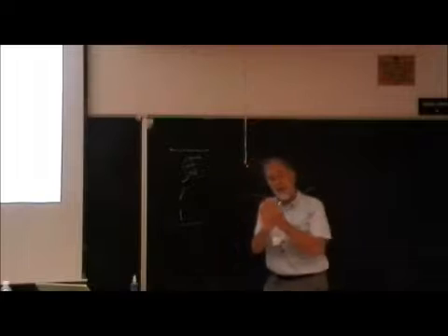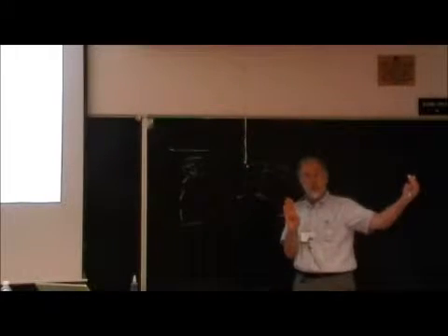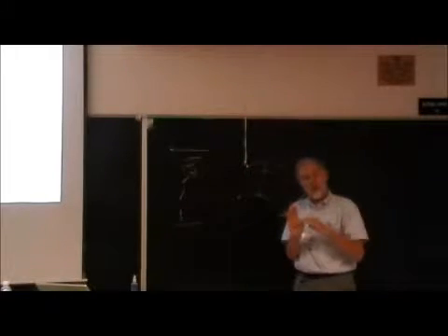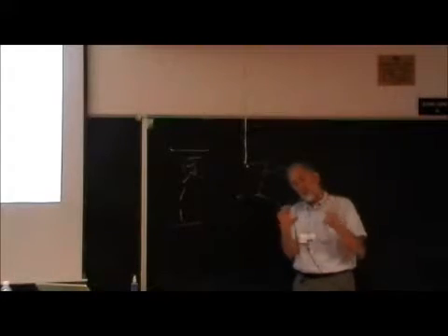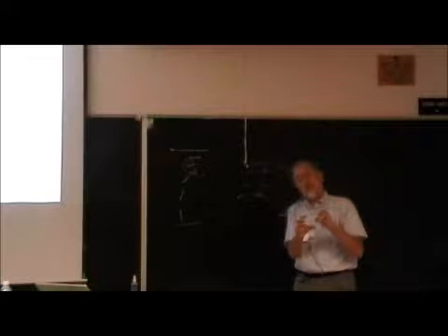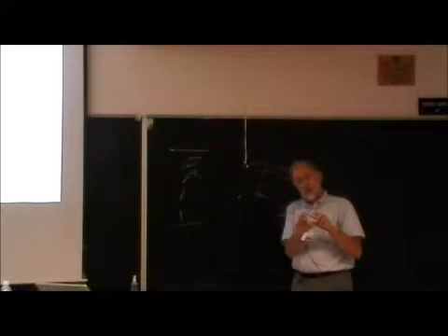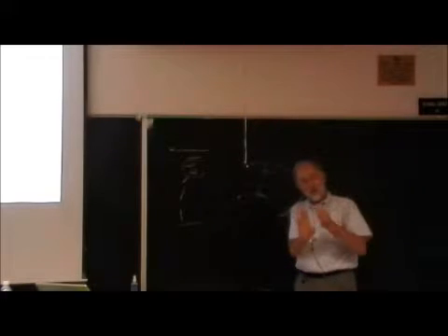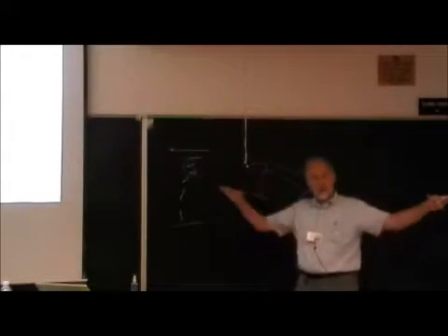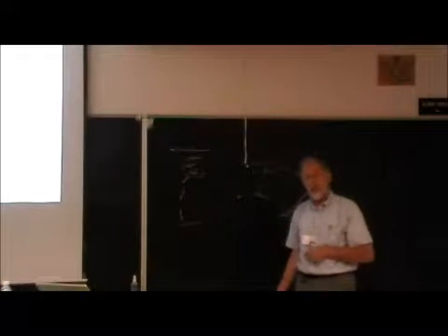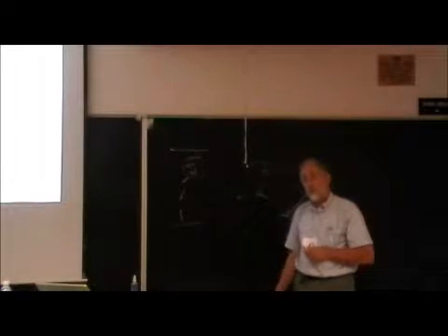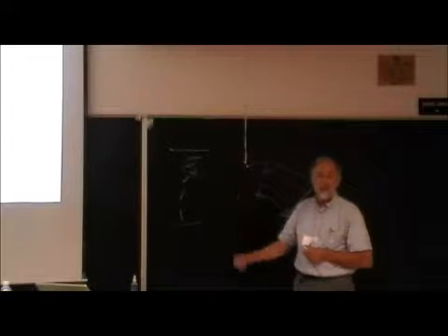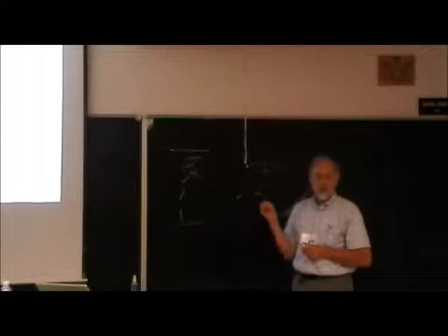So now in the chiral nematic part of that story, as you approach this phase transition, the little smectic domains appear in the nematic. They don't like to twist. So in the chiral nematic, you have a certain pitch at high temperature, but as you approach this phase transition, the pitch gets longer and longer because it gets harder and harder to twist. That's how you make mood rings and liquid crystal thermometers.